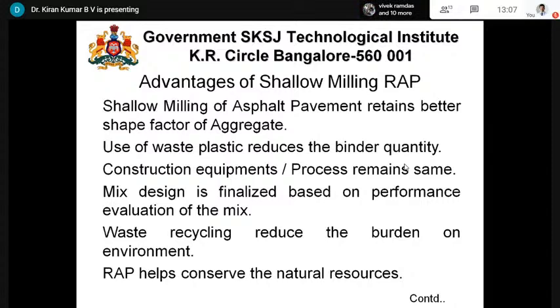supplied by adding additional virgin aggregate of 50%. In our case, we have added only 20% of the virgin aggregate. So the use of waste plastic reduces the binder quantity here. That is a clear advantage to us. The most important thing is that we have not changed the construction equipment or the process. We have not burdened the contractor or the design process. We have kept the same and we have tried to solve the problem at our end, using a back end, and giving them the solution.